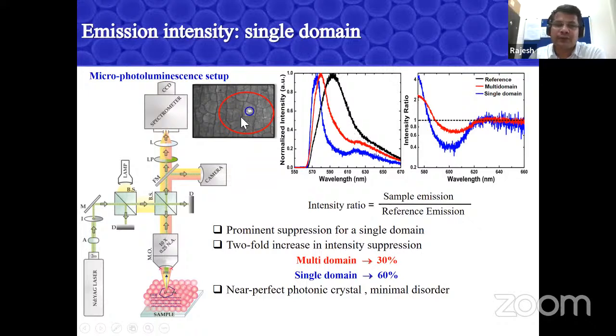Okay. And if you look at the small region, which is a single domain, the resulting curve is a blue curve. And you can see two things. One is there's a peak slightly shifted, and you see there is a bit of suppression in the emission intensity. That means the dye molecule, which is supposed to emit at 600 nanometer, is unable to come out of the system. And that is because the emission wavelength of this dye is comparable to the band gap wavelength.